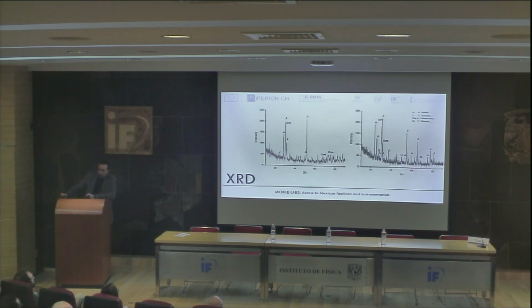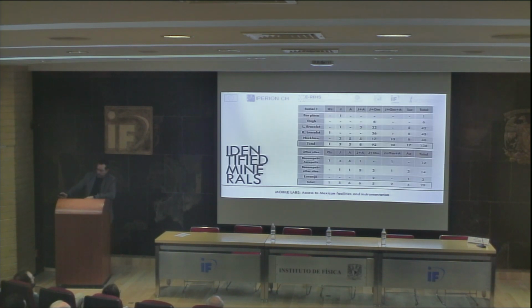And when these two are not conclusive, we turn to X-ray diffraction because it's better, very precise, but it takes a longer time. You can get the infrared and Raman results in about 30 seconds, but you need 15 to 30 minutes for each sample on the X-ray diffraction. So we set this kind of flow so only the difficult ones went for X-ray diffraction to be sure. And then we're able to identify almost all of the mineral phases present in the samples.